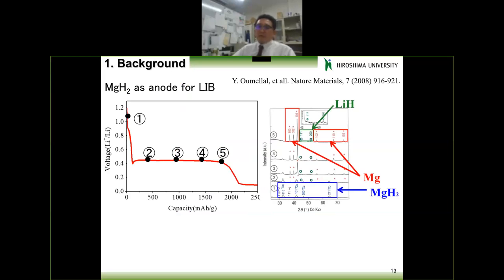Actually, in 2008, one French group reported magnesium hydride as an anode for lithium-ion batteries. Usually graphite is quite famous for lithium-ion batteries, but it has only 370 capacity. And this y-axis is voltage. In the case of graphite, at 0.1 volt, it shows about 372 milliampere hour per gram.